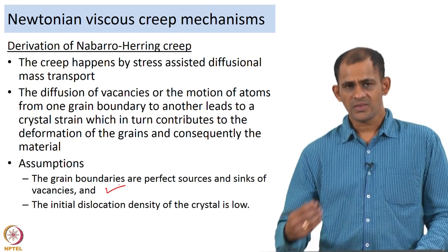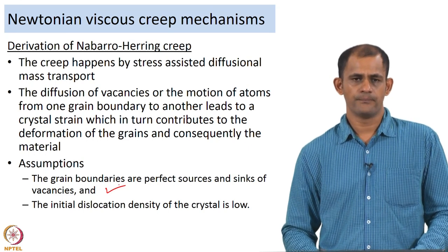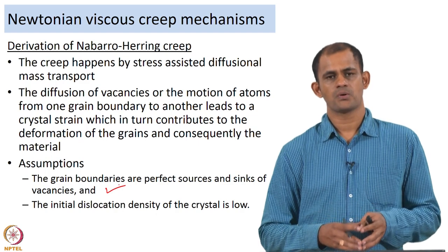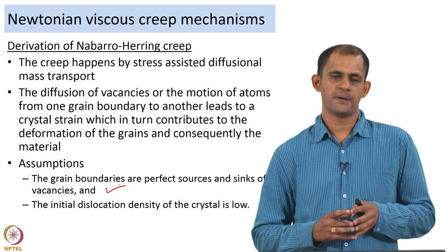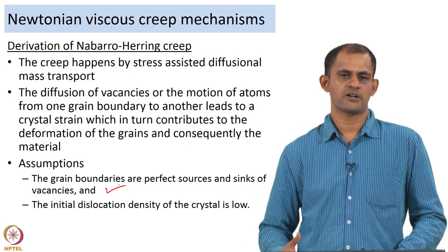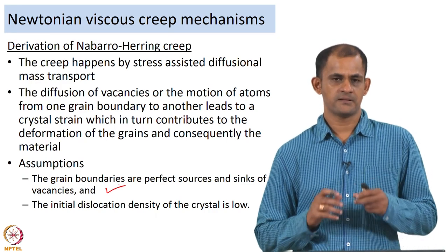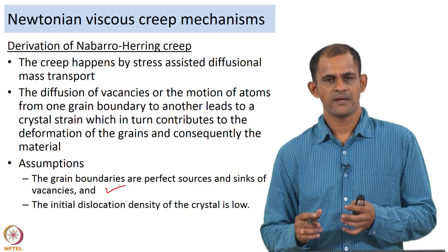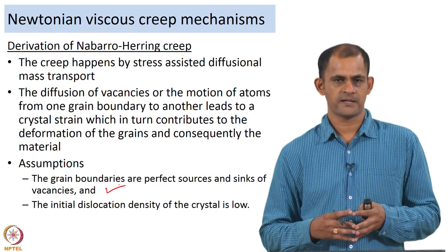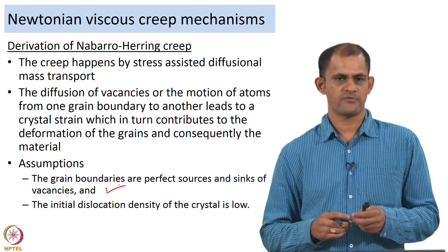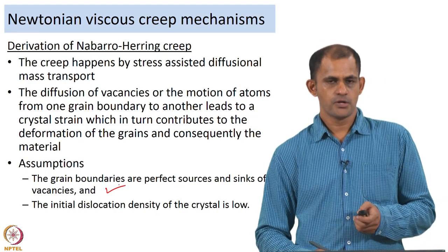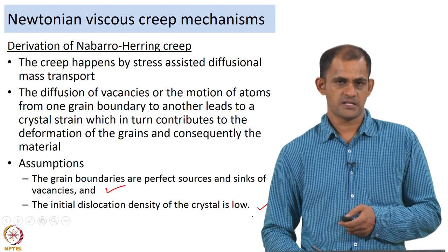The second assumption is that the initial dislocation density of the crystal is very low. The reason is we want plastic deformation to happen only by diffusion of vacancies. If the dislocation density is high, dislocations will invariably start contributing to plastic deformation, adding a dislocation-motion component that makes the Nabarro-Herring strain rate derivation complicated. With these two assumptions, the equation derivation can proceed.